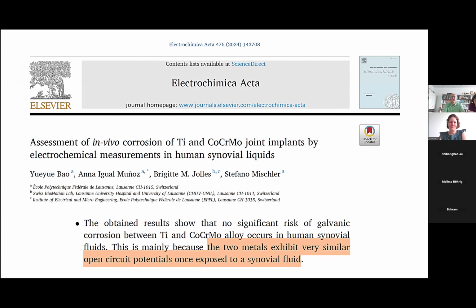And I think it was a very nice study, having a look, for example, at what happened between titanium and cobalt chrome in human synovia. And the conclusion is very clear. The two metals exhibit very similar open circuit potential, and therefore there is no galvanic corrosion between cobalt chrome and titanium alloy in the human body.